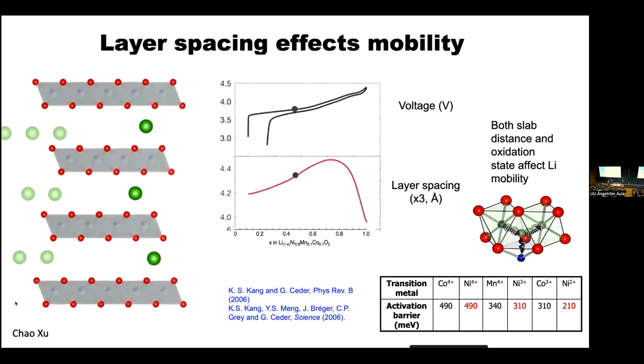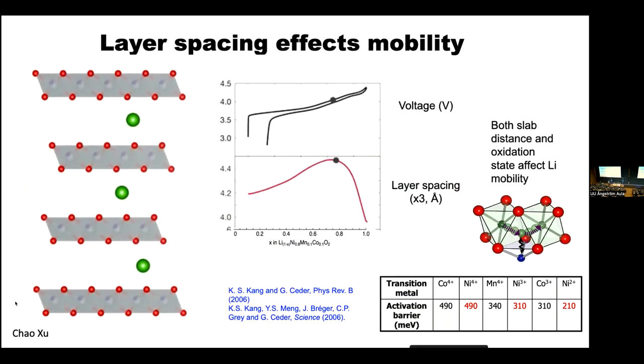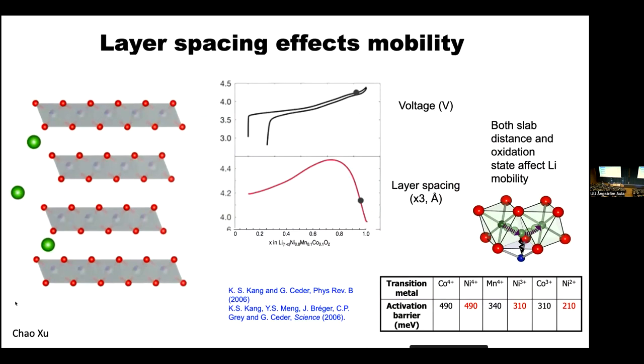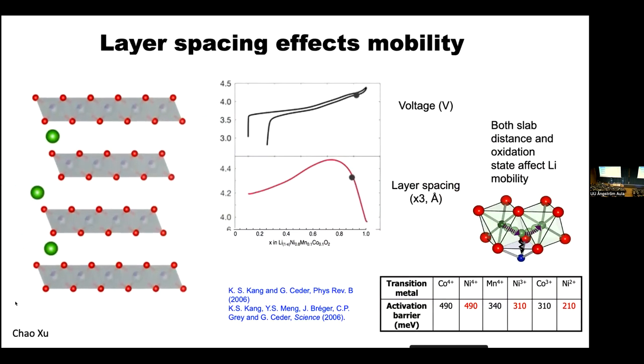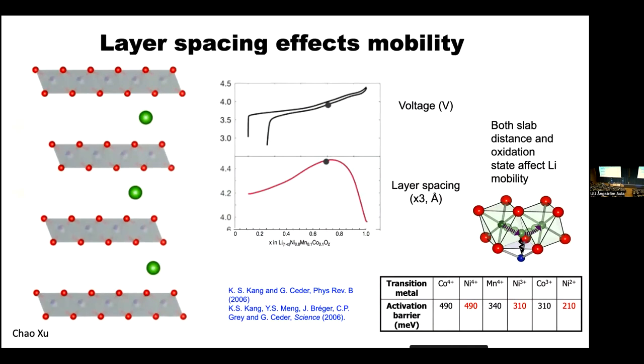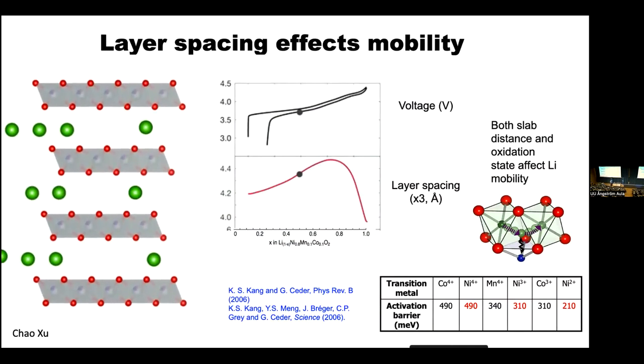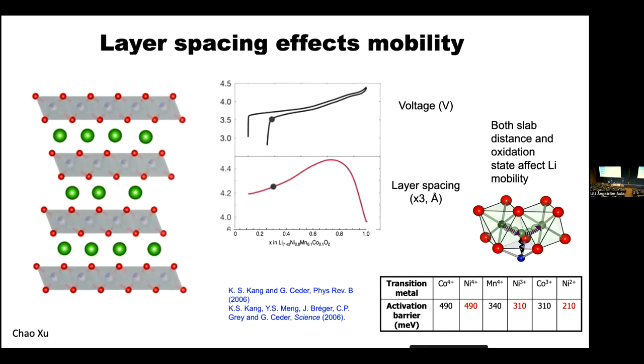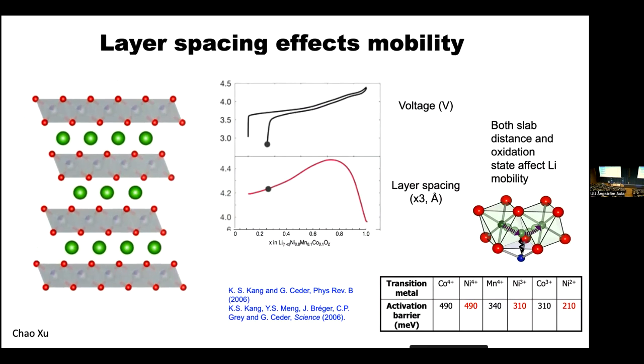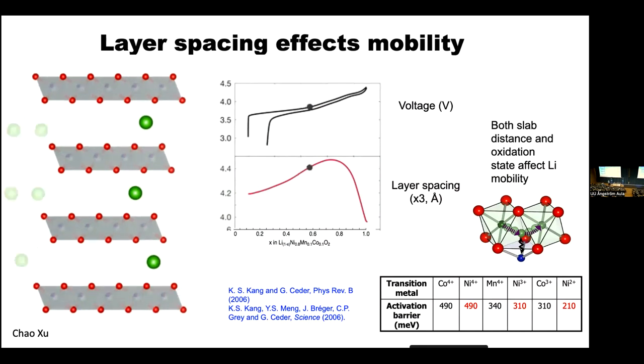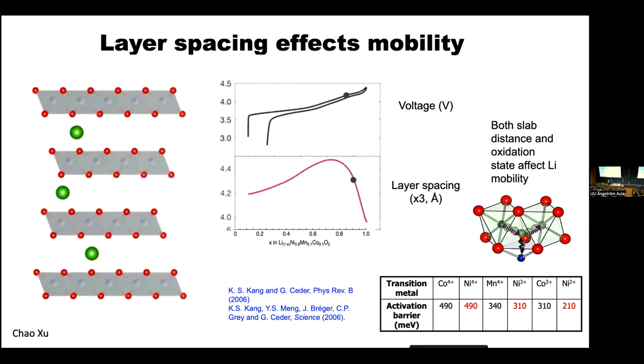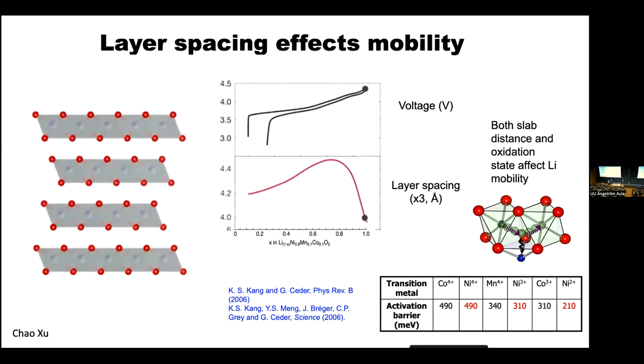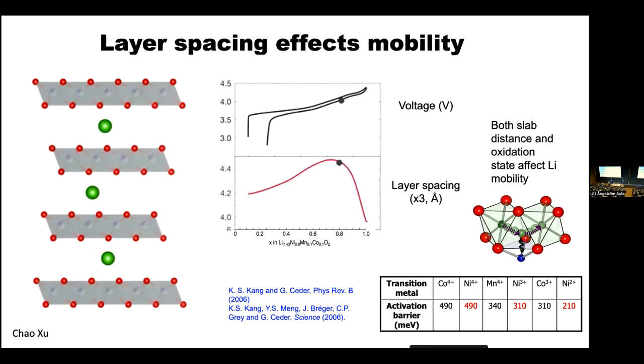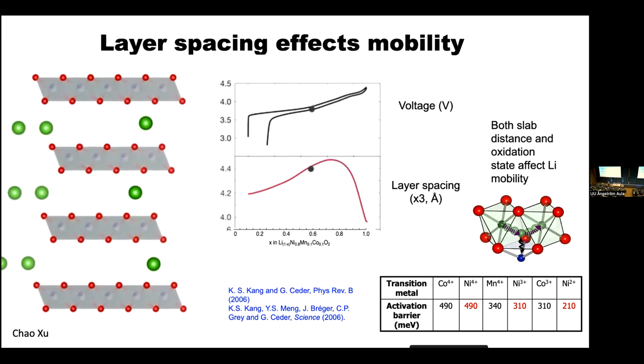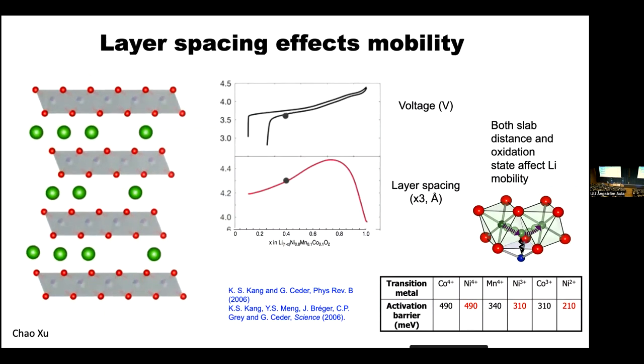So the layers are coming in and they're clamping the lithiums in place. There's a little cartoon made by my former postdoc, Chao Xu, that I wanted to show. He's an alum of Uppsala University who came to my lab for a number of years, and I'll talk about his work later. I just wanted to make one other point. You've got this concept of the layers moving up and down, but you've also got the fact that if you hop from octahedral site to octahedral site via a tetrahedral site, there's a very close contact with the metal layer below and above, and when those metal layers contain ions that are charged to 4+, then the activation barrier increases because of this very short contact. And this was work that I was involved in many years ago.